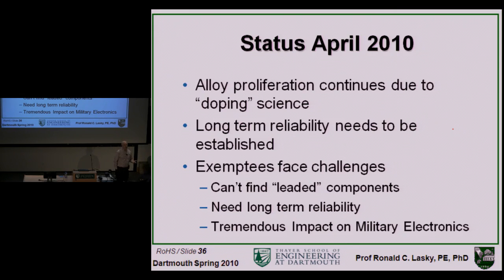What people have to do to survive in the world of lead-free if they have an exemption and plan on using lead-free solder. And I would never suggest that military people should use lead-free solder, because many of our military devices are manufactured and sit in a warehouse in Louisiana for 15 years before they go to war. As amazed as those of us a little older can be, who remember the technology of the first Gulf War and how impressed we were with cruise missiles, that was fought in 1991, and much of the military technology that was implemented was made in the 70s and sat in a warehouse and still has to work. And so the long-term reliability just has not been demonstrated.